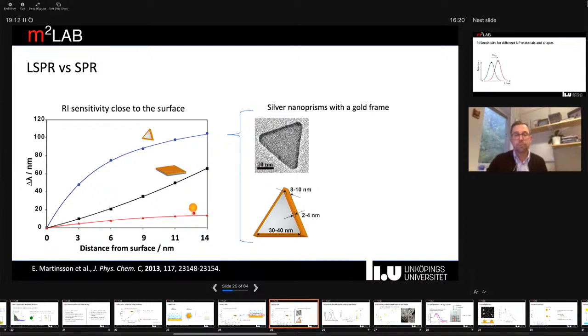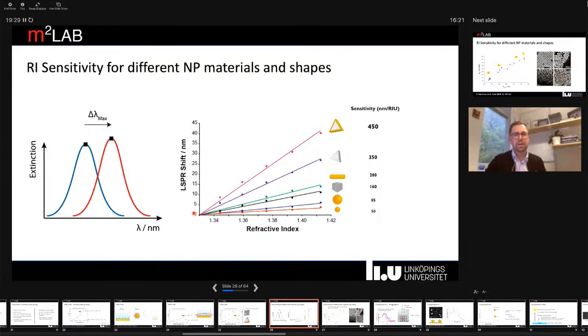So obviously, we have quite a large dependence here, as you can see, of the refractive index sensitivity on what kind of particles we use. And we can compete with SPR in this instance. These gold frame silver nanoprisms are relatively good with respect to sensitivity. But we see that there are also other particles that can perform rather well. Some are less complicated to synthesize as compared to these prisms. And the reason for having this gold frame, I should say, is that silver, although it has good sensing performance, is very sensitive to oxidation. So in order to retain the morphology or geometry of these prisms, we protected them with this gold layer.